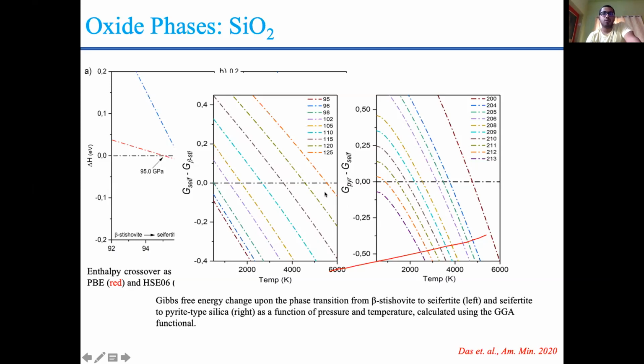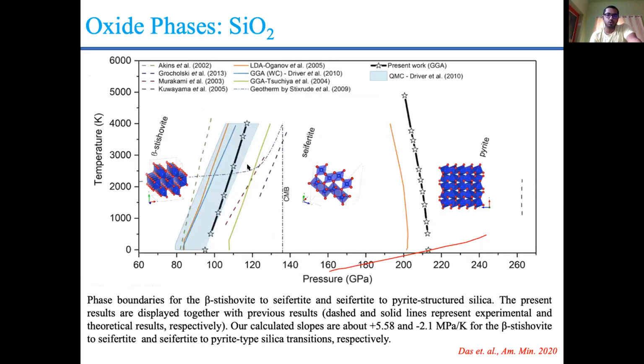In the outcome of these two figures, in the left panel, you can see the transition temperature increases with pressure, resulting in a positive Clapeyron slope. Whereas in the right panel, you can see the temperature decreases with pressure, which means it will result in a negative Clapeyron slope. So here is our final phase diagram. These two thick black lines are my results. It already agrees well with the experiments.